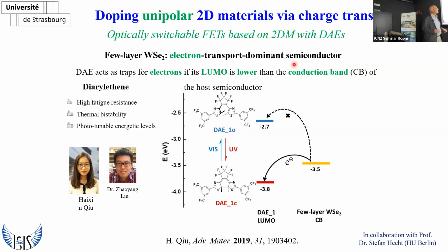So the idea is very simple. We take the tungsten diselenide, whose conduction band is 3.5 eV, and we designed and synthesized with Stefan Hecht, our collaborator in Berlin, a diarylethene such that its LUMO in the closed state is within the band gap of the semiconductor, and in the open state is out of the band gap. So what does this mean?